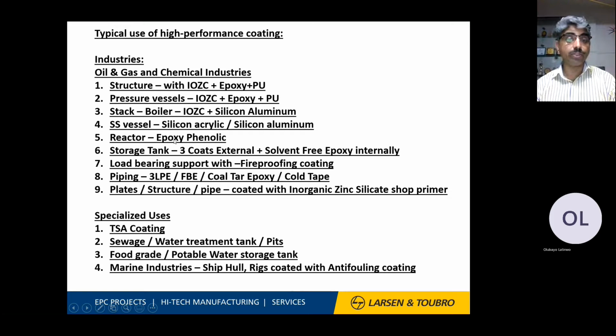Reactor again at high temperature, epoxy phenolic. Storage tank, that is again 3 coats external plus solvent-free epoxy internally, because solvent-free means it is going to give you more solids. So there is not much solvent available which is going to evaporate. So higher dry film thickness, that is for the storage tank internal.